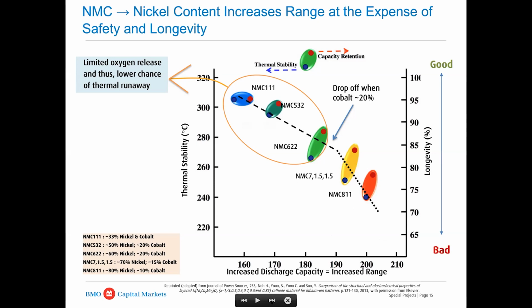And so what we see here is a perfect chart. It shows very beautifully how, as nickel increases, the thermal stability goes down, the longevity goes down. And why is that? So what exactly happened there? At first, I think the scientific consensus was that when cobalt came below the 20% mark, it would stabilize the system. And so this was actually where the circle is. That was where the industry focused on, and they tried to get to the NMC 811. They tried to get into these other elements that were not as stable.